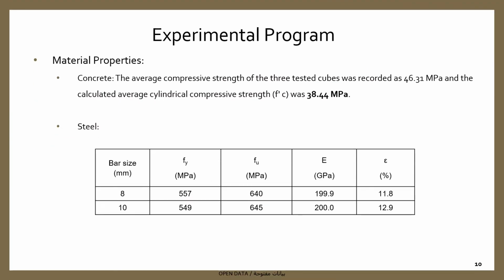Moving on to material properties, the average concrete strength of cubes was recorded to be 46.31 megapascal and the cylindrical compressive strength was 38.44 megapascal. Steel properties were recorded by applying a tensile test, then they were listed in the table below.